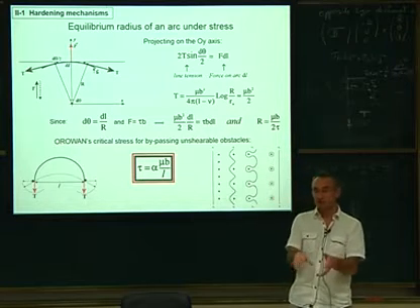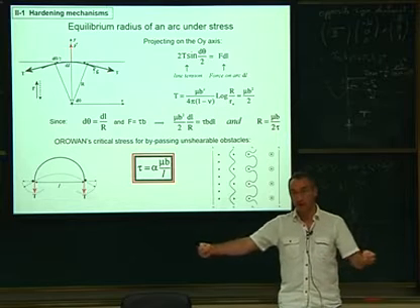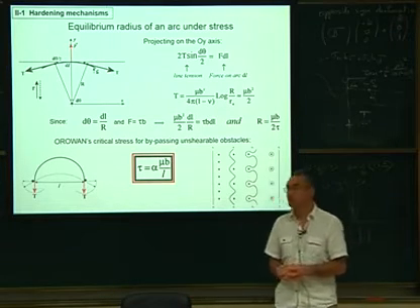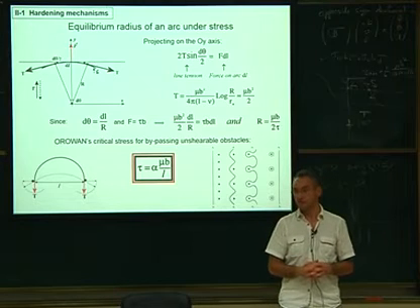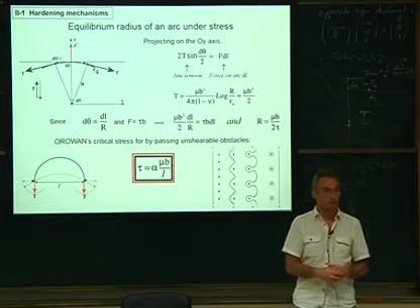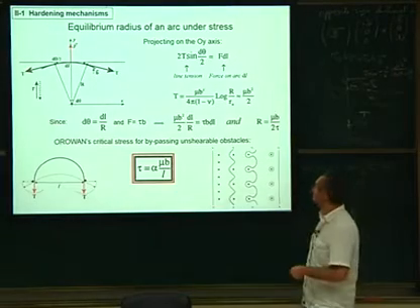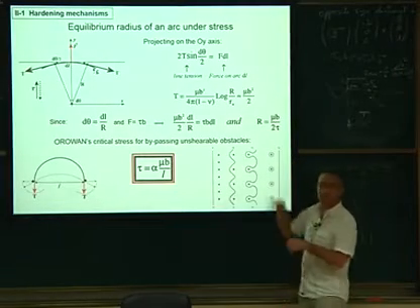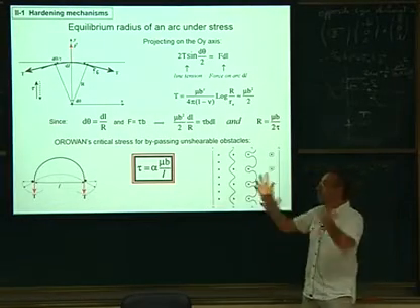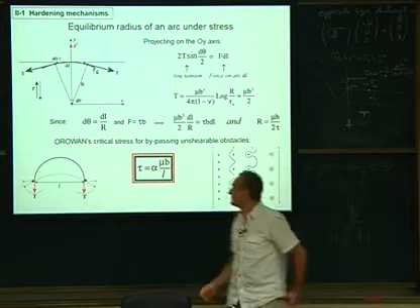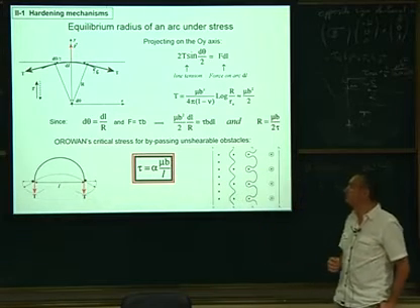So not only the stress locally that you see is coming from what you apply, but also from what is internal. I call it internal stress. So internal stress includes the thermal stresses, I agree, and also all the local stress you may have, but also dislocation segments somewhere else. So this stress is the total stress, what we call effective stress. So all the stress that could be active at that place where you have your dislocation. Okay. So that's a very important relationship for dislocations.